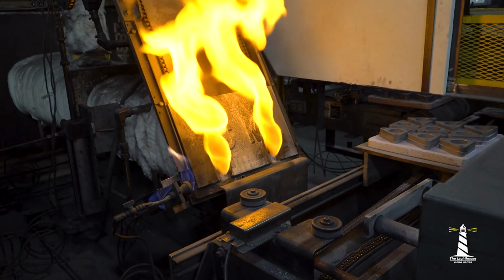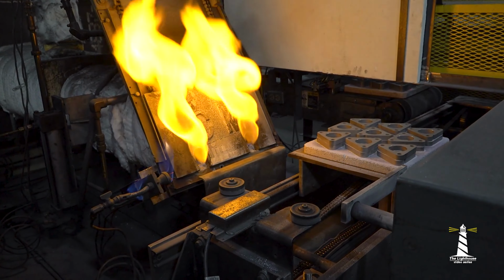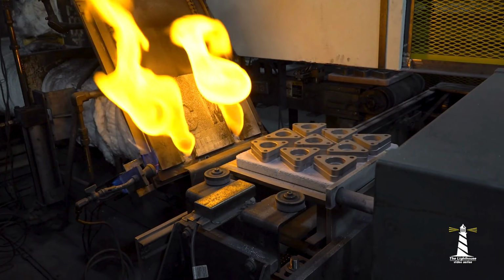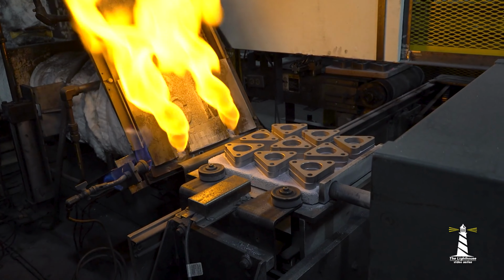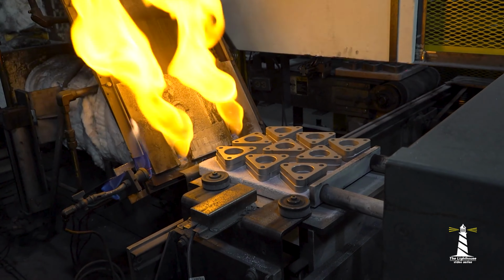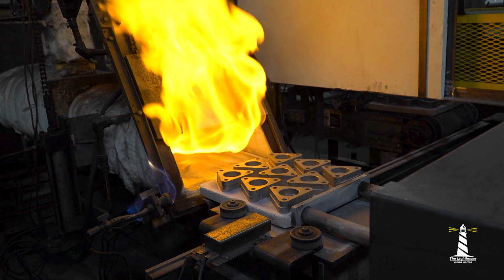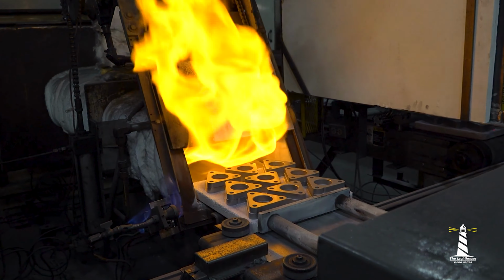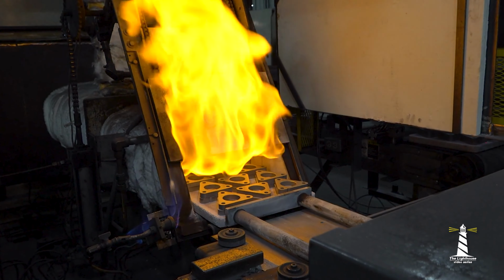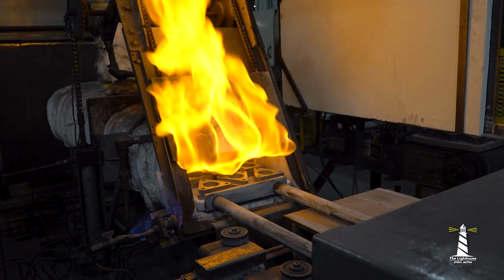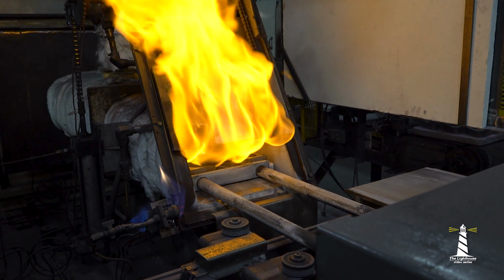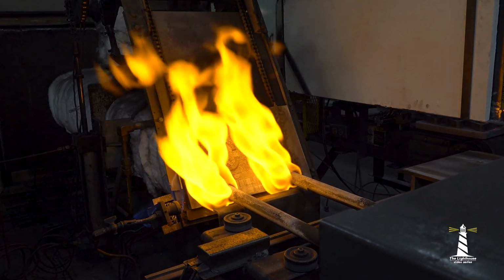Yeah, so getting beyond the compaction process, we can also pick up density in the furnace. Just in general, some materials inherently shrink through the furnace when they're heated up beyond a certain point. Right. So you get some density that way. But where we focus in our facility is actually high temperature sintering. With high temperature sintering, you are going to consolidate that material through the furnace so it actually shrinks. Right. And without changing the weight, you'll get higher density through that. You can get up to around 95, 96% density through that.